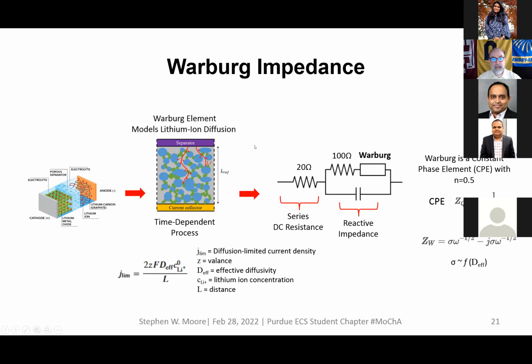But in the physical domain, it actually means something. So if I look at this little cartoon of what a lithium-ion battery looks like, and I have these little dots over here that's supposed to represent my lithium metal oxide, and then I take a look at what that lithium metal oxide looks like, it's actually physical particles. So you can actually see it under a scanning electron microscope. It's actually got a lot of particles in there. And the lithium ions physically have to move through these particles to find a place to reside. And so you see these little red lines, that's the lithium ion going into these particles, finding somewhere to live. And that is a time-dependent process of diffusion. And so the Warburg impedance tries to model this time-dependent process.